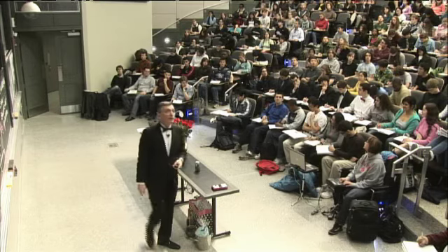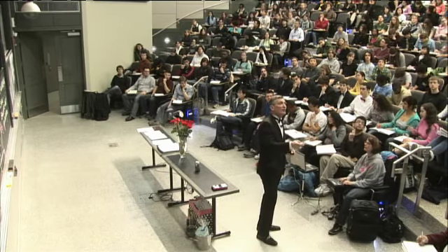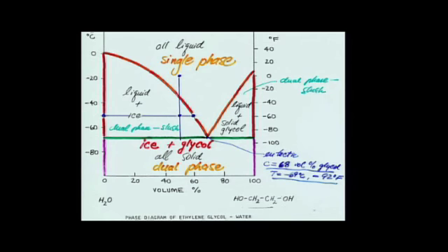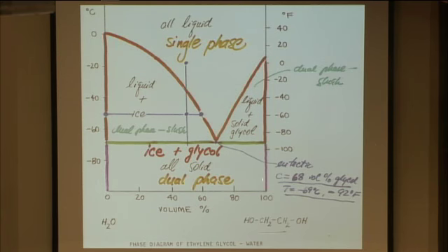All right. This is a good one. Now that winter is upon us, this is the antifreeze diagram. So on the left I have pure water, and on the right I have pure ethylene glycol. And as you can see, if you add glycol to water, you get freezing point depression. If you add water to glycol, you get freezing point depression, with a eutectic here at roughly 2/3.